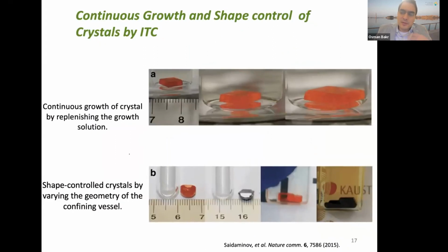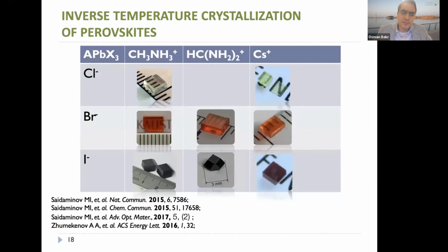And what we found is that you could keep repeating this process and you can perpetually keep growing your crystal bigger and bigger. And what was surprising as well for us, it was a tiny observation back then, but we realized it was a very important observation later on, and I'll explain to you why, that we could grow these crystals in the shape of the vessel they form using this method. So whatever vessel we put them in, the crystals take that shape. And I'll show you why that's important.